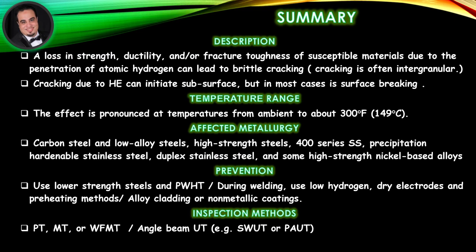Summary — Description: A loss in strength, ductility, and/or fracture toughness of susceptible materials due to the penetration of atomic hydrogen can lead to brittle cracking. Cracking is often intergranular. Cracking due to hydrogen embrittlement can initiate subsurface, but in most cases is surface breaking. Temperature Range: The effect is pronounced at temperatures from ambient to about 300°F.